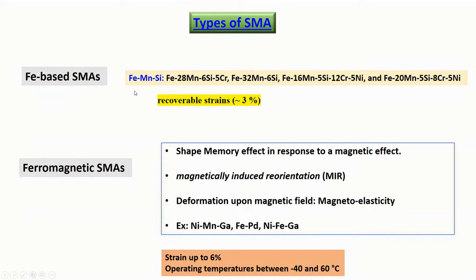And there are different kinds of shape memory alloys within the Fe-based SMAs itself, but particularly they are an alloy of iron, manganese, and silicon with different compositions. And we can get a recoverable strain of around 3%. Now, this recoverable strain means that if you are pulling a material, you know that up to a certain extent, it can recover its shape completely. So if you're pulling it up to a certain stress and unload it, it will come back to its original form itself.